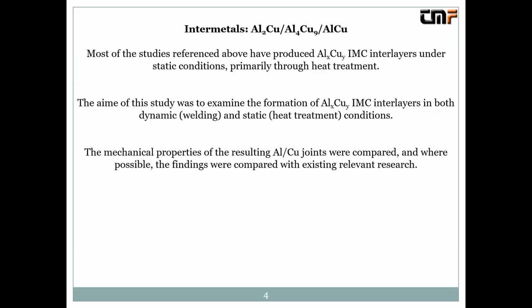And what's the importance of mentioning the variety of the intermetallic compounds? The strength of the interlayers, because between each compound it is wholly different. So before our investigation, we knew that the strength of the intermetallic layers is weaker than the strength between intermetallic layers and the pure aluminum or pure copper. But during these investigations, we have found out that the effects of AlxCuy intermetallic compounds might be crucial in terms of improving strength during exploitation. So, as I said, our aim was to investigate first of all the formation of those intermetallic compounds during dynamic and static conditions. In terms of dynamic conditions, we mean welding, and static, the heat treatment.